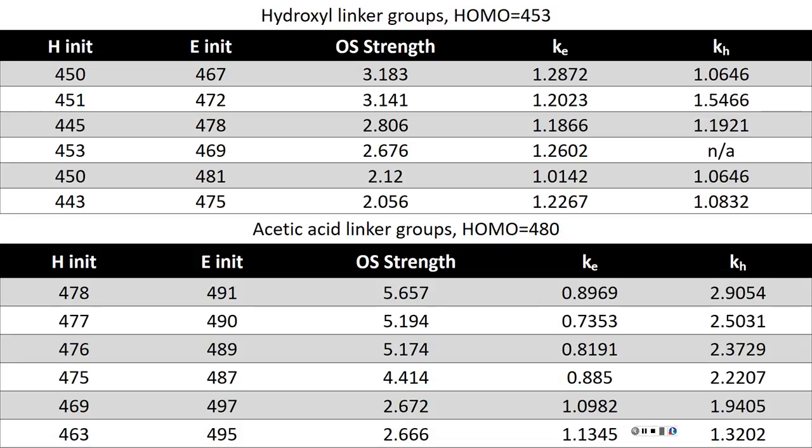For a combination, it will be a fixed number for a given system. It will not change depending on excitation. Once it gets to HOMO and LUMO, it will be the same rate. It's how quickly you reach the lowest possible transition, or the optical band gap, in other words. So you start wherever your energy is, probably far away from the band gap, but you end up close to the band gap.